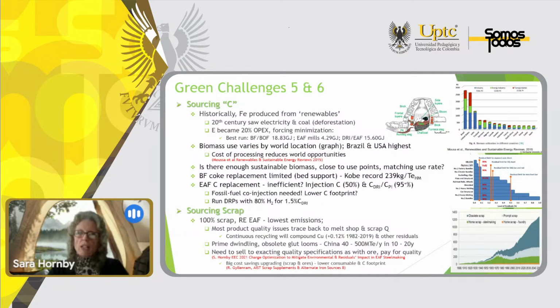Green challenge number 5 is sourcing carbon. Historically, iron has been produced with renewables, but the 20th century saw electricity and coal, because of the deforestation, come to the fore. And then, when energy became 20% of the OPEX, it forced minimization. And the numbers here in gigajoules are for the blast furnace BOF 18.8, arc furnace mills 4.3, and the DRI EAF steelmaking is 15.6. So you can see the advantage of the EAF mills from those numbers.